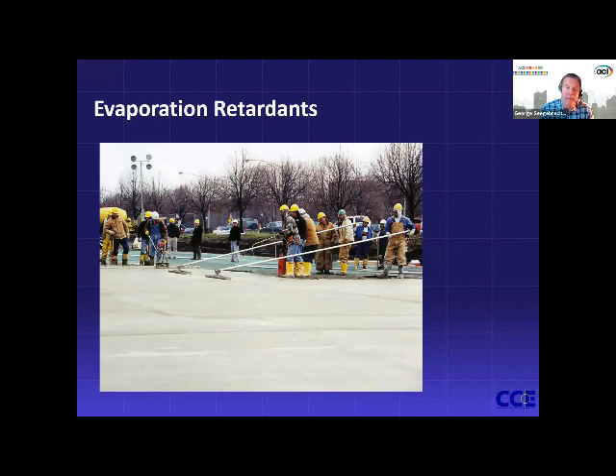Here's a job we worked on at a skating rink in Hyde Park, Chicago area. Kind of a big deal because the mix had corrosion inhibitor. We had everything going on, and a very wide, flat, open surface, and it was kind of a windy day. And the guy here with the red Hudson sprayer is spraying evaporative retardant, or they call it reducer now. Great. You can't really do anything else in this area because you have no windbreak capability here.